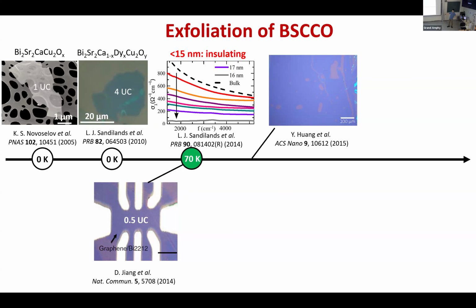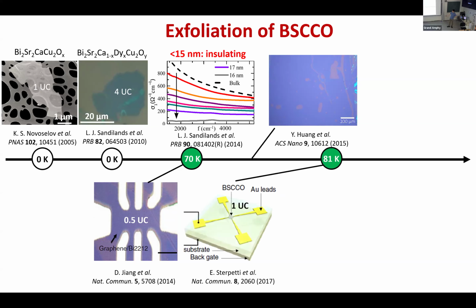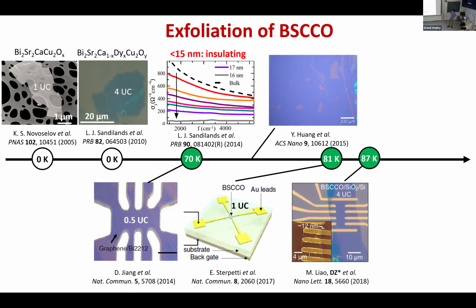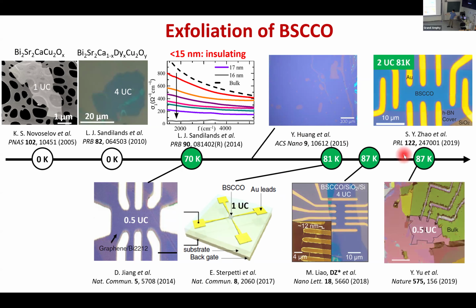In the beginning, they claimed this is a dimensionality effect: when you get a thinner film, thinner flake, you lose TC. However, people realized later that this is just because of doping, because this system is very sensitive to oxygen in the crystal. So then people improved the sample, and eventually, Zhang at Fudan University ended up having a monolayer, a half unit cell sample, with the same TC as the bulk. And they also studied, for example, STM and other things.